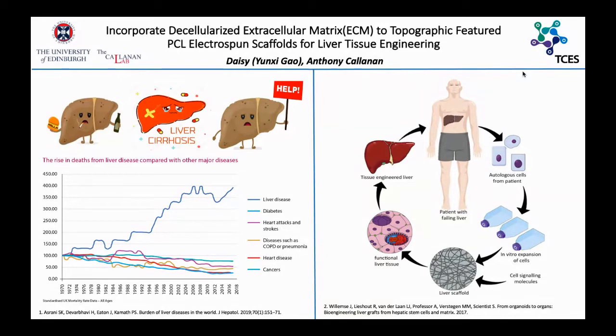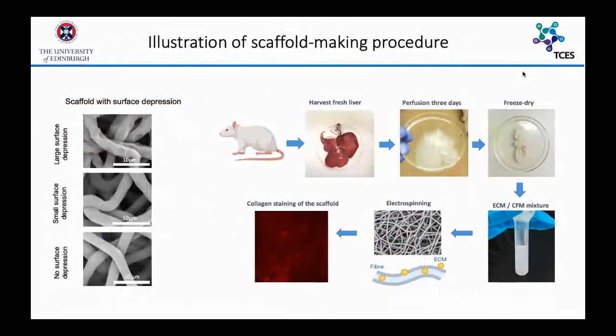Liver tissue engineering shows promise of treatment. We can design the scaffold in vitro, then grow the cells on it, then eventually turn it into tissue. Then we can use that to repair or replace damaged liver tissue, or to do disease modeling or drug testing. In my study, I use the electrospinning technique to fabricate this scaffold. In order to know how the scaffold structure and composition influence cellular performance, I first made three different types of scaffold, with fibers with large surface depression, small surface depression, and no depression.